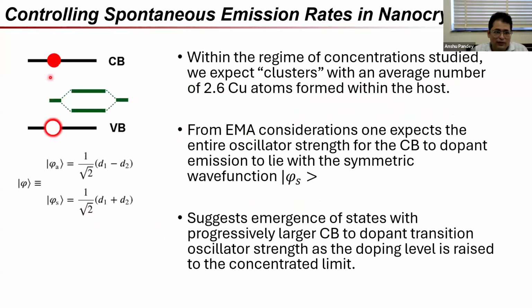So first of all, what happens? This sort of a picture is immediately connected again with undergraduate level physical chemistry courses, because we are looking at some sort of an MO diagram over here. What is happening in fact is that the states which are forming at lower energies would always have a symmetric overlap. They would be more symmetric, while the states at higher energies would be less symmetric. And the immediate consequence, spectroscopically speaking, is that all of the oscillator strength is mostly borne by these more symmetric states at the bottom. So overall, when you start adding copper, you become blind to these higher energy states.